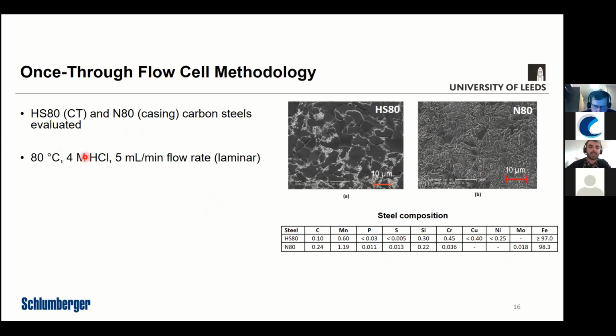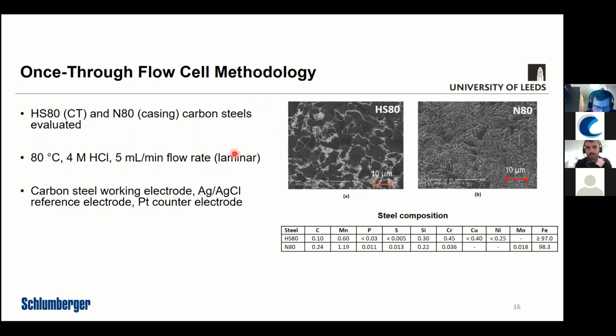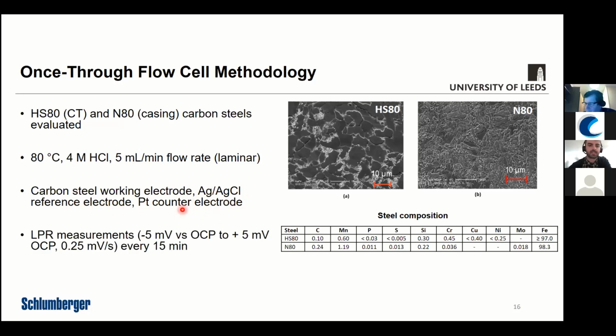So we did these experiments at 80 degrees C using 4 molar hydrochloric acid, and all at a flow rate of 5 milliliters per minute. So this would give laminar flow conditions, essentially so that we limit the limitation of using the flow cell, but also it gives us a controlled environment, and we're not necessarily looking at how hydrodynamics influence conditions in this particular study. So as I said, we do electrochemical measurements, and we'd use the carbon steel coupon as the working electrode. We'd use a silver chloride reference electrode and a platinum counter electrode to complete the electrochemical cell.